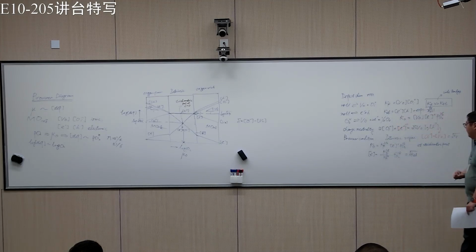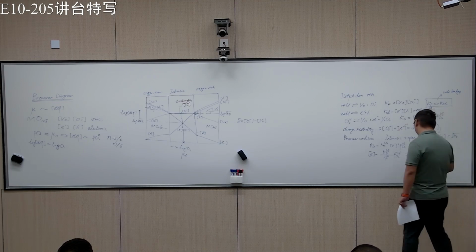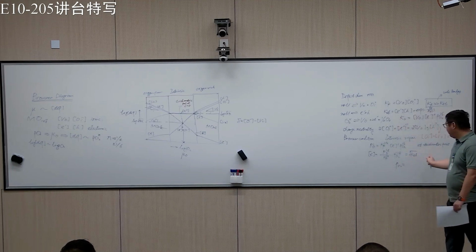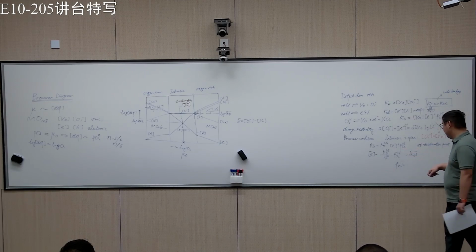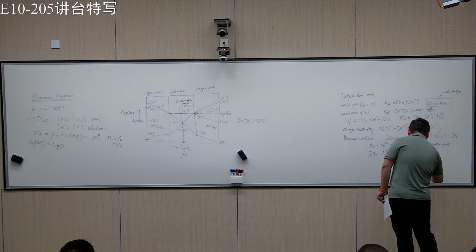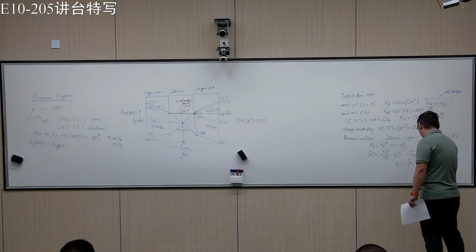Okay. Right. So then if you have this one the same as this one, you can solve for PO2. Take this here, then just get rid of the 1/4 power, you get KO squared, then KEL to the minus 1, then KF to the minus 1. Okay.